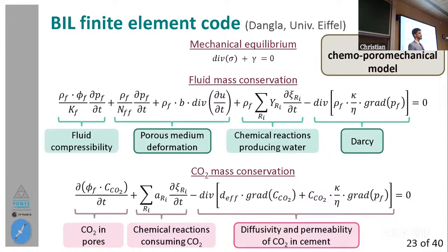Then we will have the third and final equation, which is CO2 mass conservation, which has 3 main terms, from which I'm going to focus on only one, which is related to the diffusivity and permeability of CO2 in cement. This term will also be affected by the rupture of the spheres, which will result in an increase for interconnected porosity of the material.